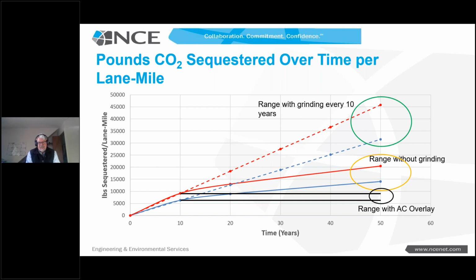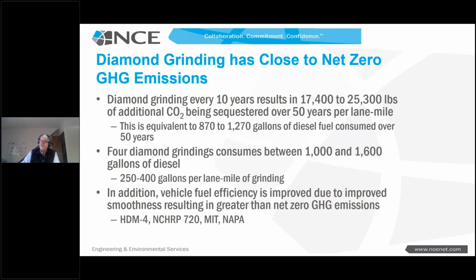And this actually talks a lot about concrete block, right? If you're looking to sequester CO2 and you paint your block, you're not really going to get much carbon sequestration there. Why I think this is interesting is if we looked at the amount of CO2 that it would take to grind, and we look at what diamond grinders consume over a lane mile of pavement, we almost end up being carbon neutral with that diamond grinding.